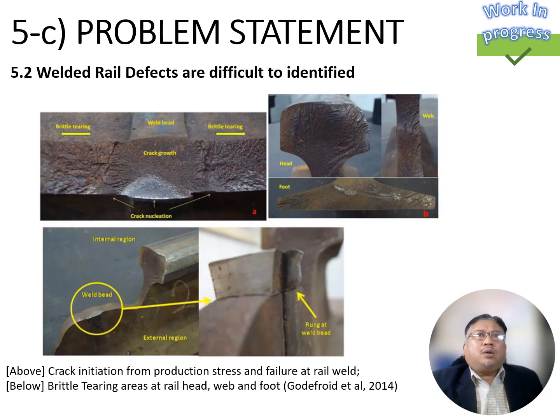Welded rail defects are also difficult to identify. The industry has agreed that crack growth in the web and cracks initiated in the head are very difficult to identify, and it requires several transducers at different angles to identify their presence. This is a very slow process and requires highly skilled workers. If the cracks are not identified or the weld is not removed from the surface, the internal crack region will propagate and extend to an uncontrollable size, and in the end this will cause the rail to break.